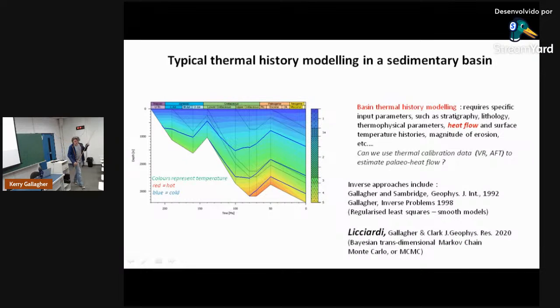So I'm going back now to the sedimentary basin case, because it's important in the oil industry. It's something I've worked on for quite a long time, trying to solve this thermal modeling problem. As I said, there's lots of stuff we don't know. Generally what we do is specify the heat flow, make these calculations, and compare our predictions to our calibration data, so the vitrinite reflectance or fission track data, and say whether we can fit the data with this certain heat flow history or not. That can take a lot of time. It's often a little bit subjective.